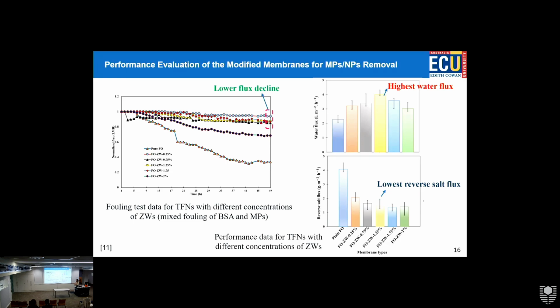This one is the plain membrane without any modification. As you see, after 1 hour, it starts to decline in terms of efficiency, water flux. This one is the sample with the highest concentration of zwitterions. Normally we have a threshold above which we have deterioration of the properties because of the agglomeration of the materials that have been put into the structure of that sample. But with the medium range of the concentration, we can see that we don't have the loss of permeability. Basically, we have more stable flux over time, which is highly advantageous in terms of the durability of the membranes.